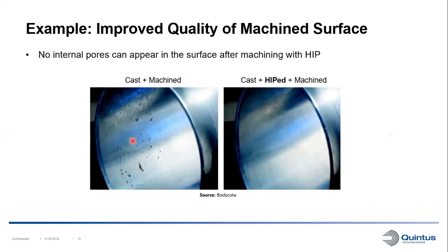Here's an example of the improved machined surfaces with HIPing. On the left here, we have a cast tube whose inner surface has been machined. As we can see, we have revealed quite a lot of internal porosity in that surface. So this is, of course, not optimal. On the right here, we have the same type of cast tube that has been HIPed before it was machined. And as we can see, we have a virtually perfect surface.